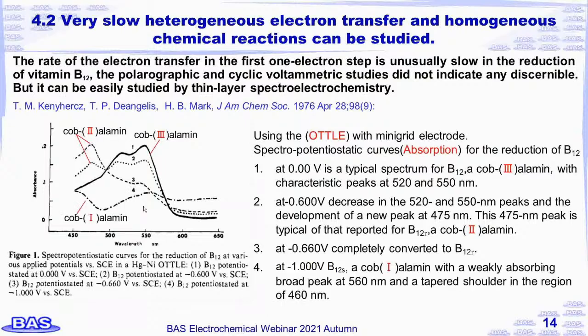This peak is typical of that reported for B12r, a cob(II)alamin. Curve 3 at minus 0.66 volt is completely converted to a cob(II)alamin. Curve 4 is at minus 1.0 volt for B12s, a cob(I)alamin, with a weakly absorbing broad peak at 560 nanometers and a tapered shoulder in the region of 460 nanometers.